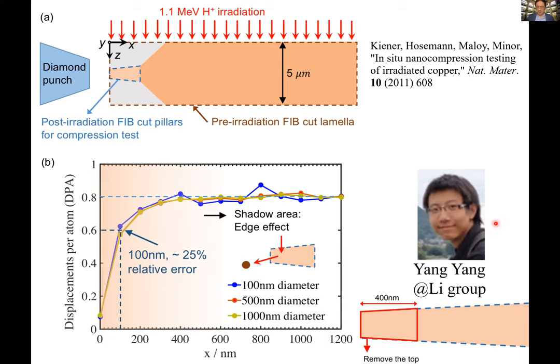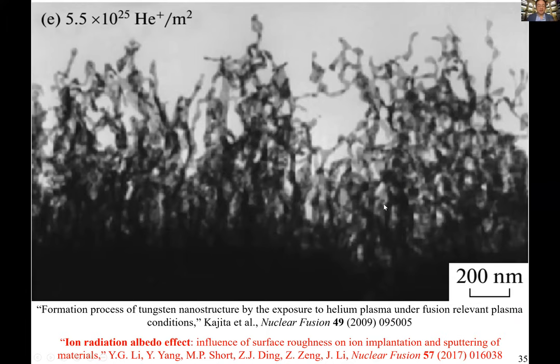But what my ex-student Yang Yang showed is that after this exposure, you actually have to cut out the first 400 nanometers of the tip from the surface, because you have a lot of ion leakage from the surface. So your DPA is not what the theory tells you. So you have to cut this initial head off.